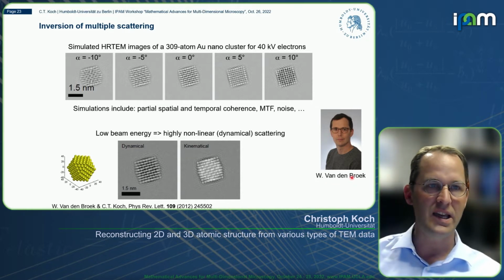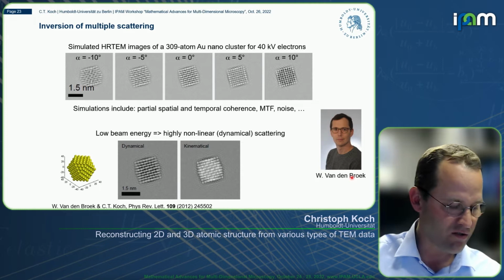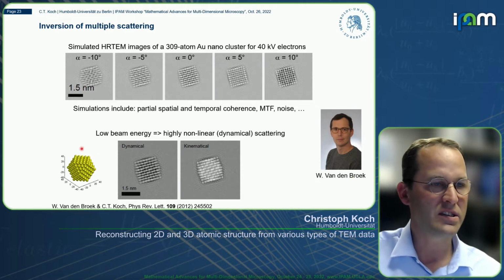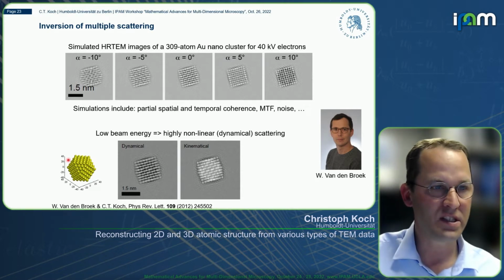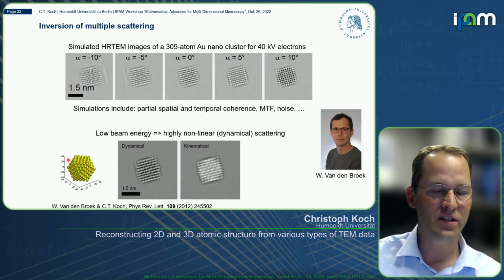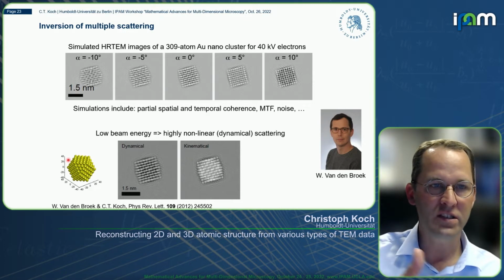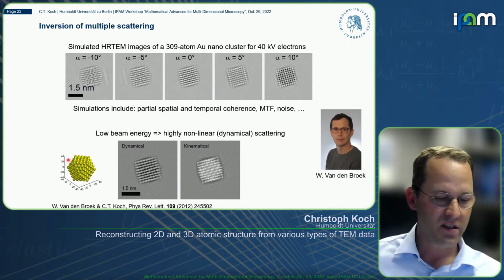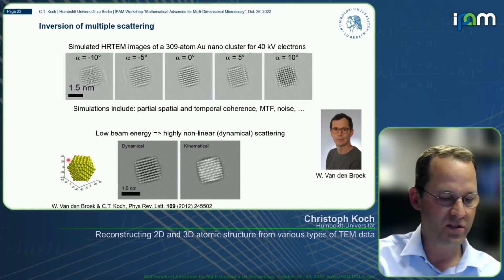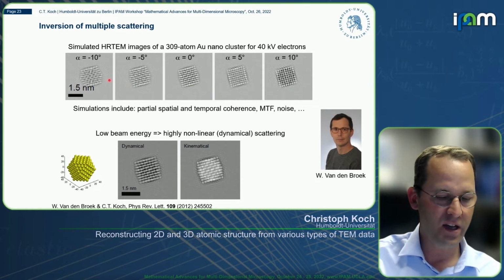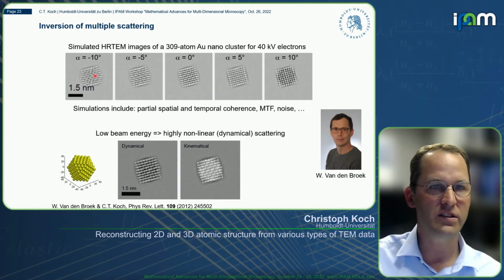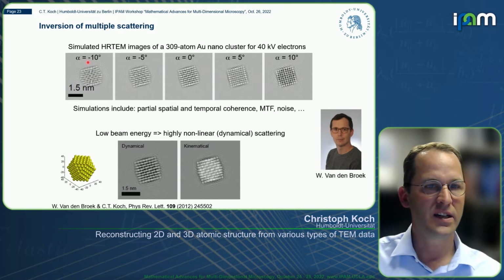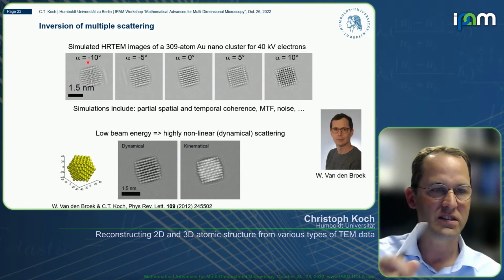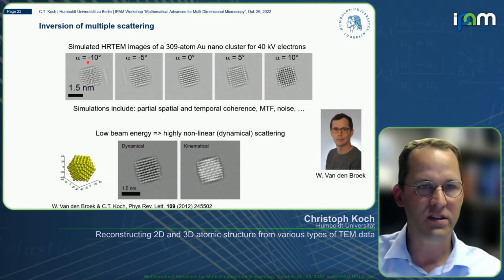So his aim was to reconstruct the atomic structure of something like this gold nanoparticle here, or see whether this can be done just from high resolution TEM images. And he found out actually there's enough information about the 3D structure, the position of all these atoms, if you tilt the sample, or in principle, you could even just do this by tilting the beam by only plus minus 10 degrees in both directions, in both alpha and also beta. So you don't need to have a full 360 or plus minus 70 or whatever tomographic tilt series.